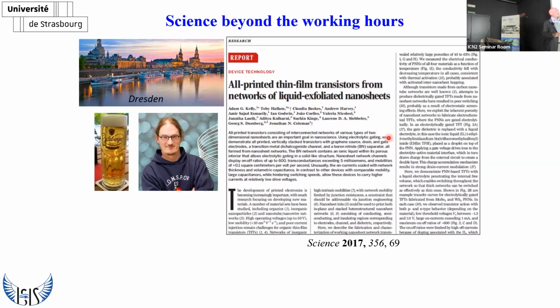Now, here there were a number of things that I was unhappy with in this paper. First, he used the term network, which we still disagree on, because I will tell you in a second why for me network is not what he published. And second, I was unhappy with the fact that he makes these molybdenum disulfide transistor devices with mobility that was, let's say, pretty low, 10 to the minus 2, 10 to the minus 3 centimeters square per volt per second. So I told him this kind of mobility you can reach with organics in a much better manner.